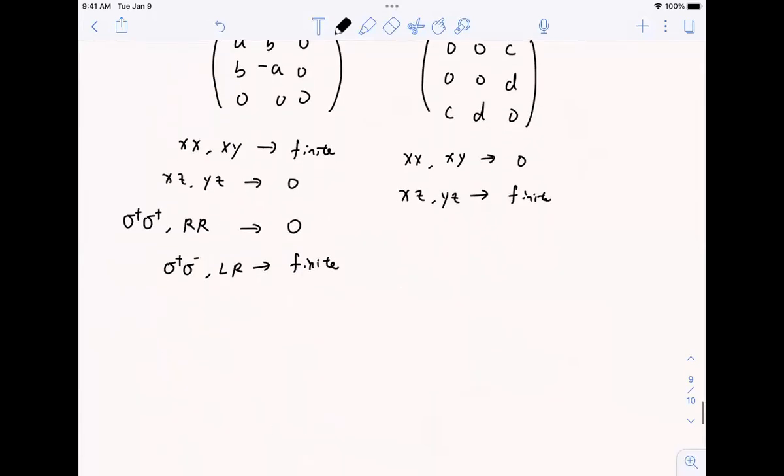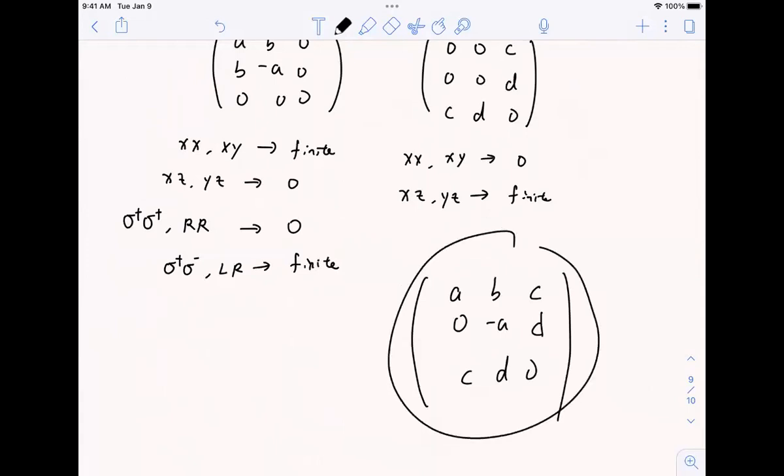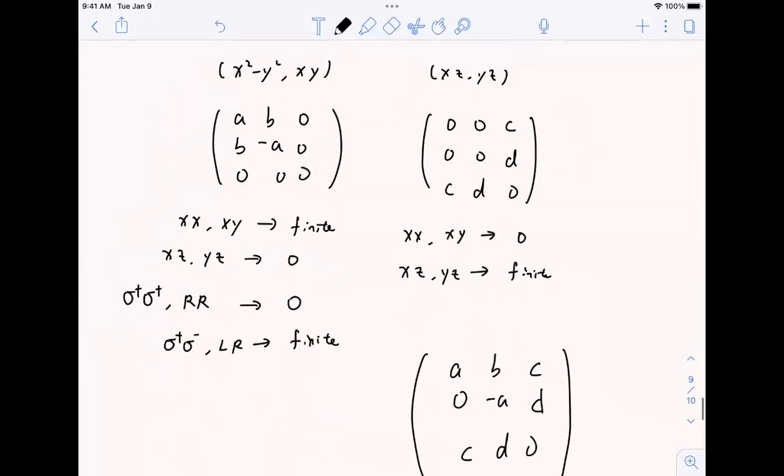The Raman tensor is not like this. You cannot sum them together. Yes, the sum is a representation, but not an irreducible representation. All the eigenmodes must belong to one irreducible representation, so it's either this one or this one. That means group theory cannot tell you which one it is. You need to go into more detail to see whether it is this one or this one.